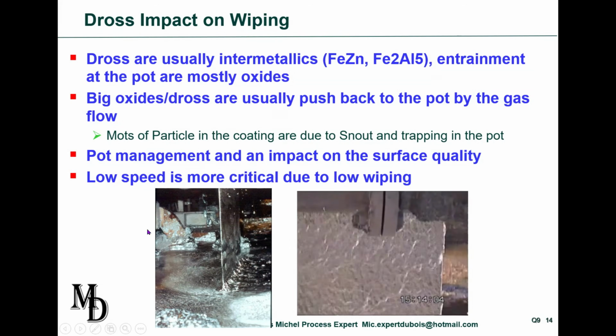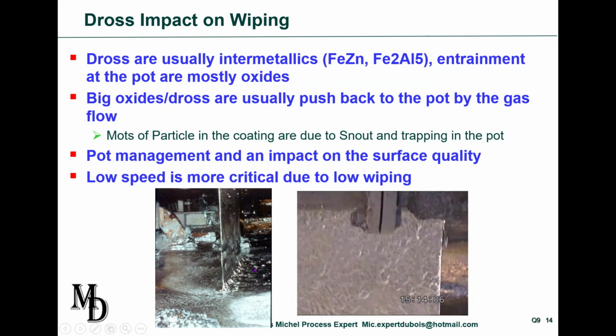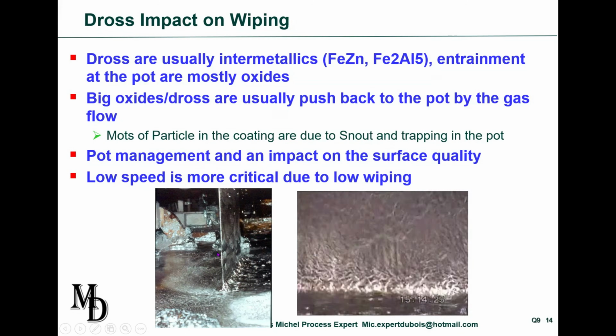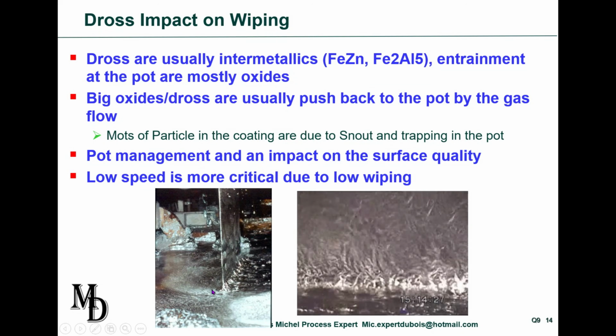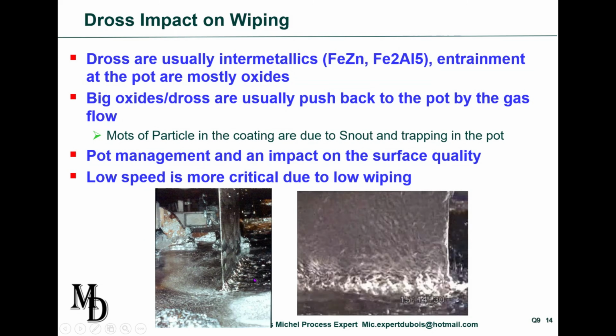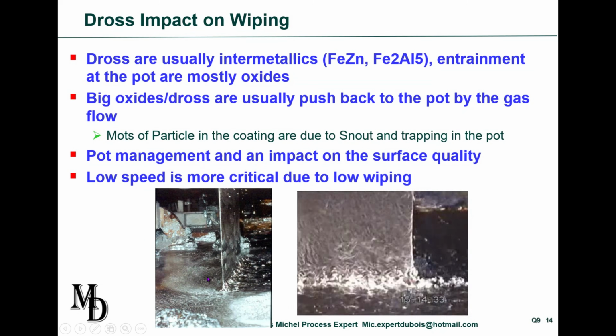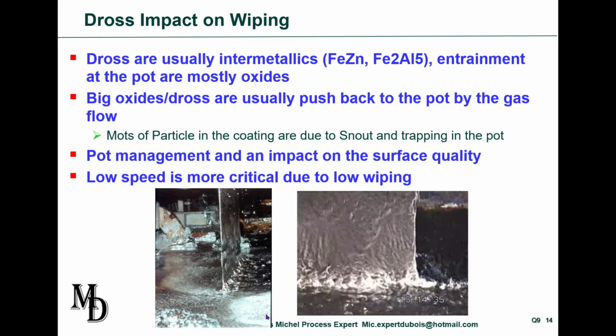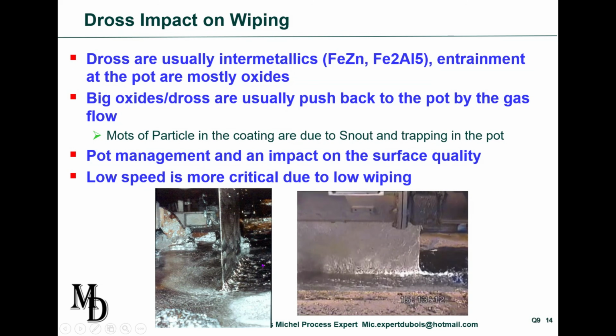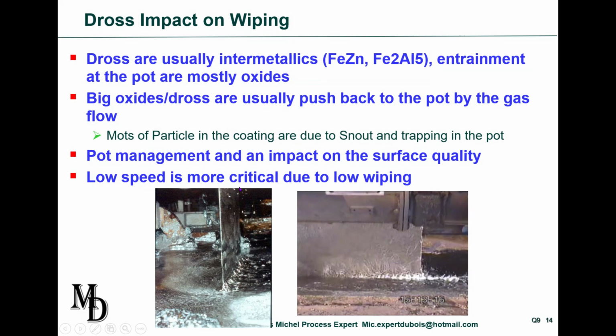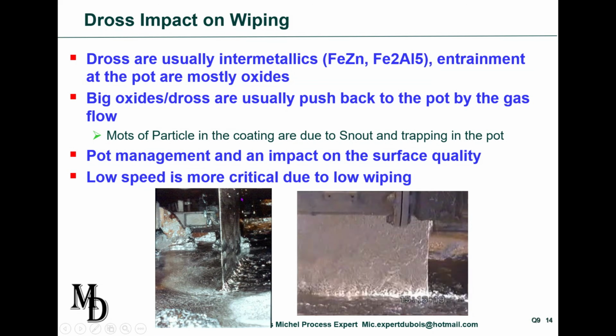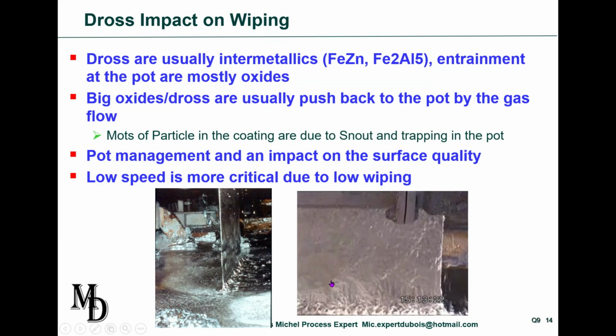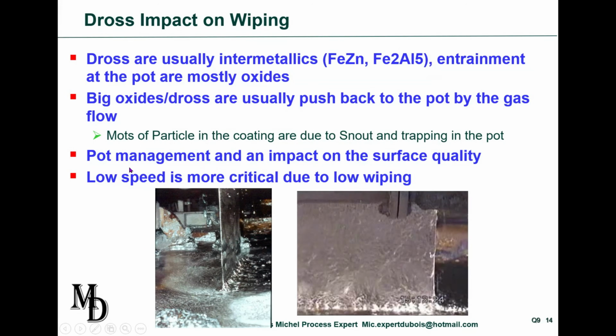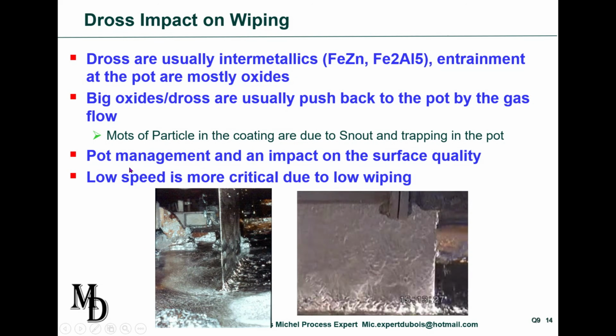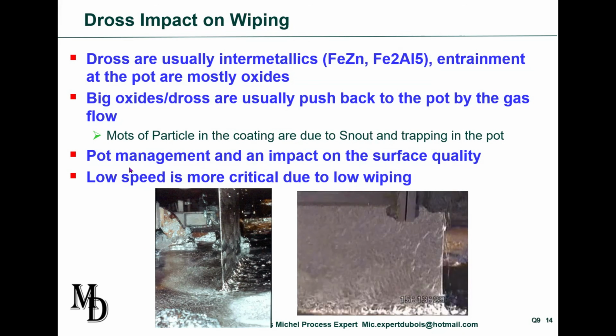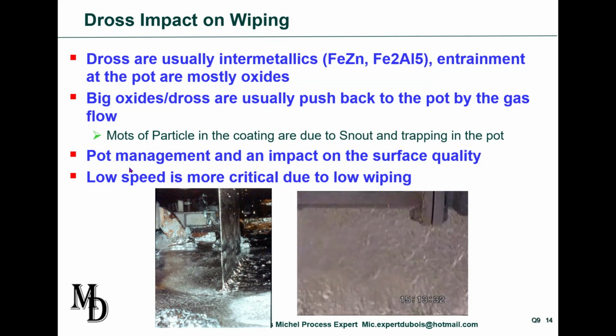On the previous pictures that I showed you, you see on this one, for example, the reason why we have the skimmings contacting the strip on one side and not the other is related to the pot walls. Very strange, but it is indeed that one. And if on this side we have no dross sticking to the strip, it's because the gas flow going down is pushing the dross away. So, of course, pot management has an impact on surface quality. This is where it's very important to control that.